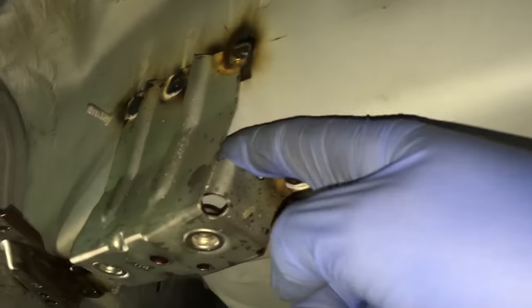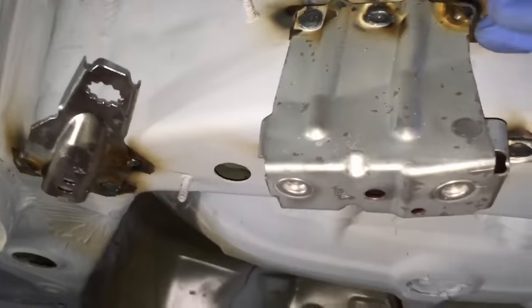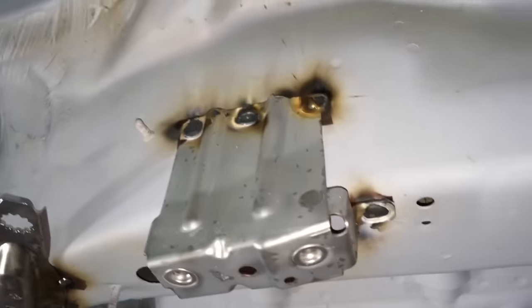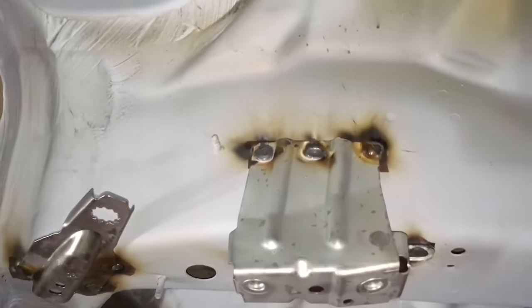So I'd much rather have the back of this area here with etch primer rather than copper weld through. So that's what I've done. I've just made the bare minimum amount of copper on the squares that I needed to, so that behind the welded contacts there is some protection, basically. So that's what they look like when they've just been plug welded on.